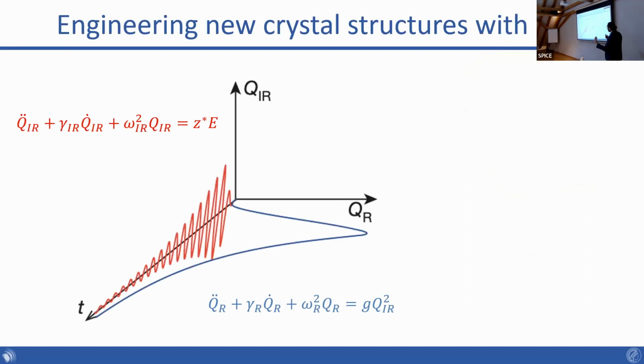And so you can see how this looks in the time domain by writing the equations of motion from the energies that I wrote down. In red is the equation of motion for the infrared active mode that I excite with light. As you see, it just vibrates back and forth. And in blue, I'm showing you the equation of motion for the coupled Q_R mode, which is driven by this Q_IR squared. And you can see that basically, while this thing is ringing, you're going to get this displacement of this Q_R mode.